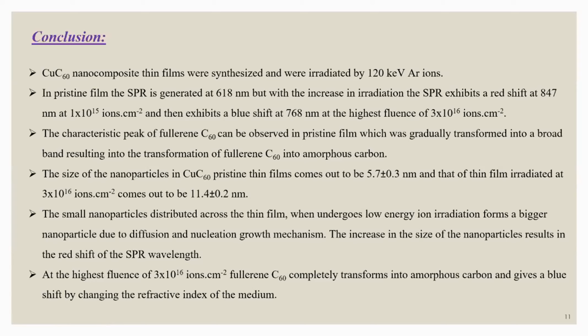The small nanoparticles distributed across the thin films, when undergoing low energy ion irradiation, form bigger nanoparticles due to a diffusion and nucleation growth mechanism. The increase in the size of the nanoparticles results in the redshift of the SPR wavelength. At the highest fluence of 3E16, fullerene C60 completely transforms into amorphous carbon, which gives a blue shift by changing the refractive index of the medium.